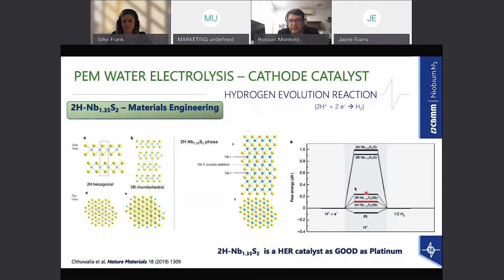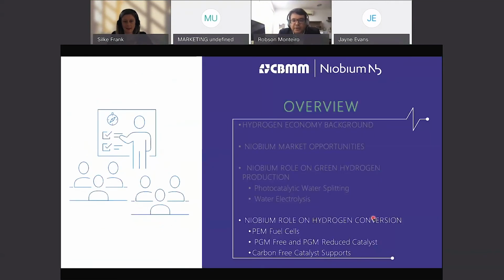And if you see in the energy diagram here, it reduced remarkably the energy needed to drive the hydrogen evolution reaction and make the material pretty close to the performance of platinum. And this material is as good as platinum. So let's jump, for the last part, since I'm running out of time, to hydrogen conversion.